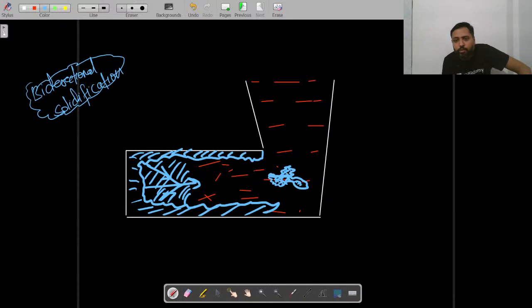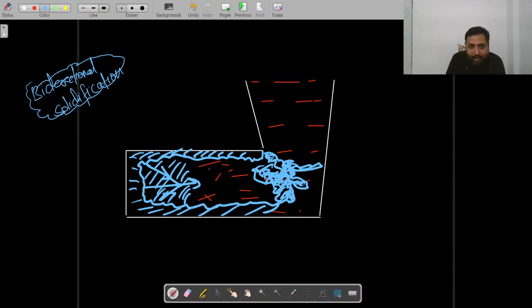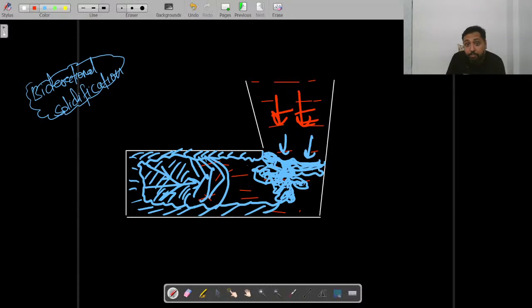Due to that non-uniform thermal gradient, suppose this solidification front formed here, meaning solidification also started at that point, and this front will start to move towards this direction. As it moves, it is increasing in size. After some time, this road through which the molten metal from the sprue cavity was coming back to compensate for the shrinkage has itself been blocked.